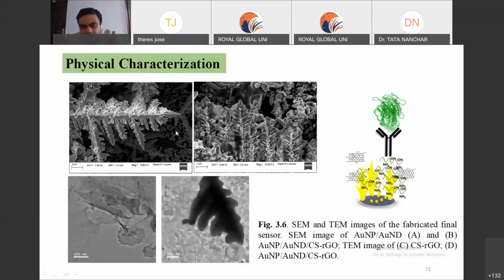And this is a physical characterization. You can see these structures are homogeneously distributed onto the chip, and they participate in the generation of ultrafast signals. We removed this material from the matrix and tested the whole sensor without it. When we removed it, the signal dropped drastically. I'm not saying the signal was not coming, but by incorporating these 3D materials in the matrix of the sensor, the signal was improved several fold. That was the beauty of this particular work.